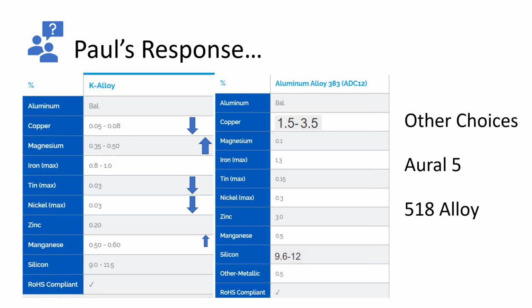Now there are other choices out there as comparisons to K alloy, and that's going to be using like an Aural 5 alloy or a 518 alloy. Now 518 is an aluminum magnesium alloy, and so magnesium is the next highest constituent material. Virtually no corrosion. It's used in high electrical and high corrosion environments for 518, but I'm going to tell you it's much more difficult to cast than Aural 5 or K alloy. The aluminum silicon alloys with good fluidity are much easier to cast than a 518 alloy, but those are just choices. So there's kind of a direct comparison of the differences between K alloy and 383.